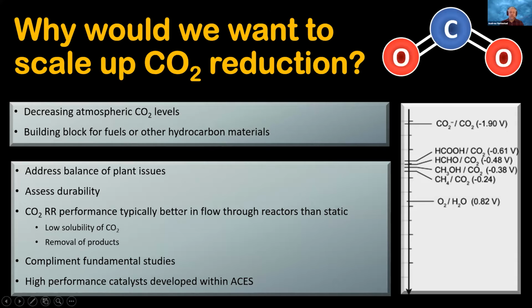So that's all the ancillary equipment that needs to go with it beyond just having everything sitting in a beaker. Also with CO2 reduction and some similar chemistries, you actually do get much better performance. If you look at the best three-electrode performance for CO2 reduction done in H cells, they're typically quite low, whereas once you switch to something like a gas diffusion electrode reactor, as I'll show in the following slides, the performances are actually better.